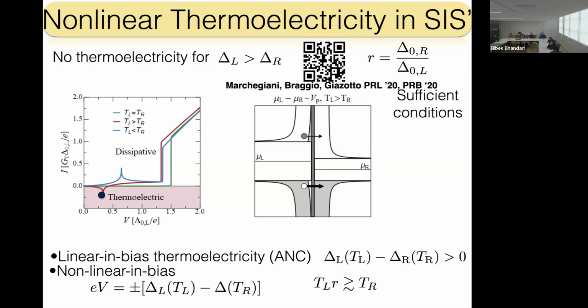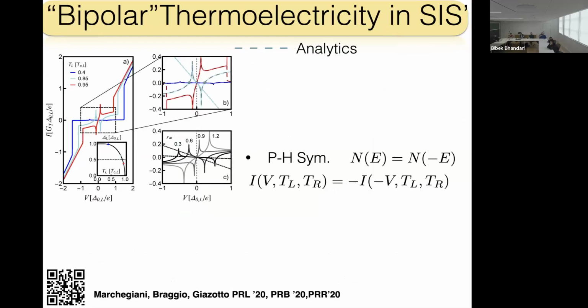However, there is another point that for me was the most puzzling when we discovered it, and this is the following. Due to the fact that you have this particle-hole symmetry in the density of states on each side, you can demonstrate that your IV is odd. So it means that there is this odd symmetry. And this odd symmetry is weird, because look at what it means. Typically in this type of system, you look at the Seebeck voltage, the voltage that you get in your system given a certain gradient of temperature.